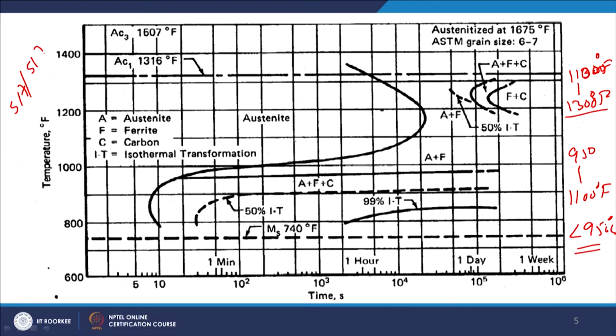So, the response of Q&T steels of the 517 or 514 type, when given exposure at a constant temperature for a longer time, the way by which austenite transforms into the different phases, that is what we can see here. So, for high temperature exposure of these steels, like 1100 to 1300 degree, this is the kind of zone for 1300 degree. What we can see here is that there will be formation of ferrite, pearlite, or maybe martensite. Mostly ferrite, pearlite and bainite are formed at a high temperature.